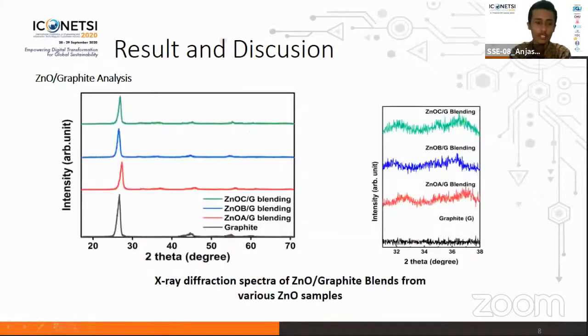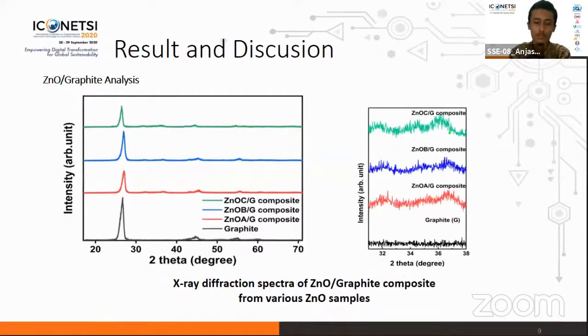And then the 10% ZnO-graphite blended and composite sample XRD spectra are displayed in this figure. The diffraction patterns show the presence of graphite and zinc oxide in every sample. There is no significant difference between the blended sample and the heated or composite sample.